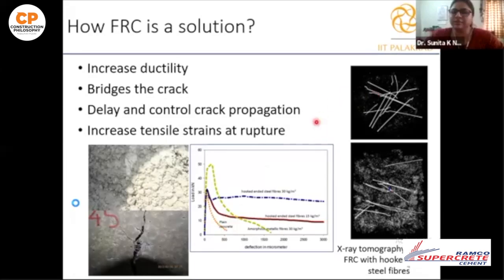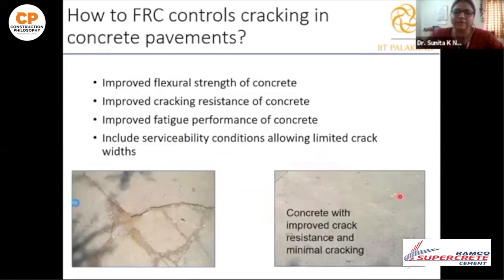So this is how fibers are distributed in the concrete matrix, so that in any direction a crack occurs, a fiber will be encountered and it prevents cracking. Let me just show you one example where these are two adjacent road pavements that are laid in one site. This is plain concrete and this is FRC concrete.